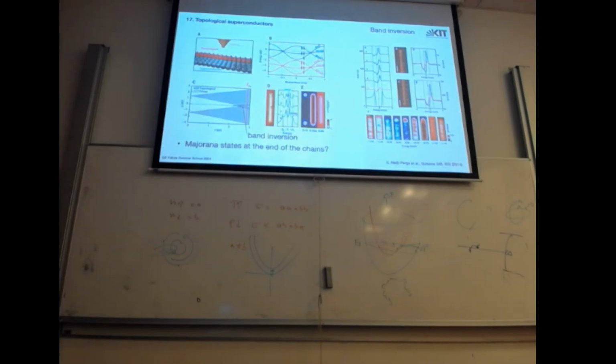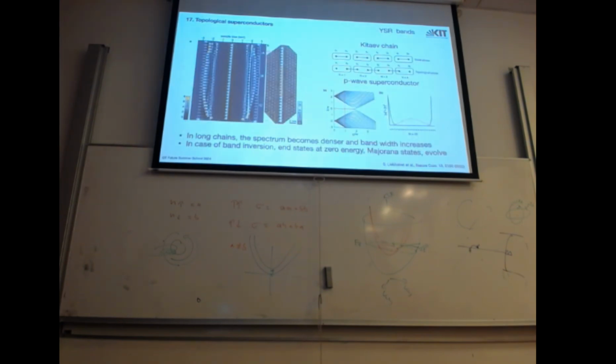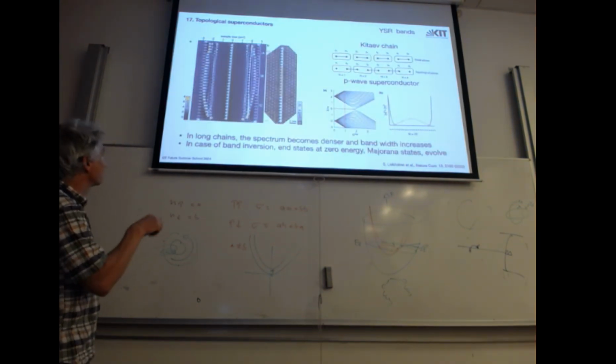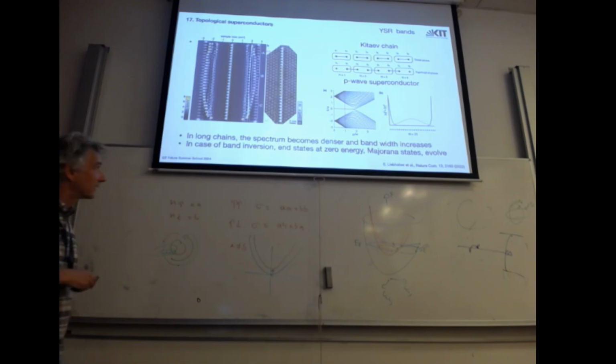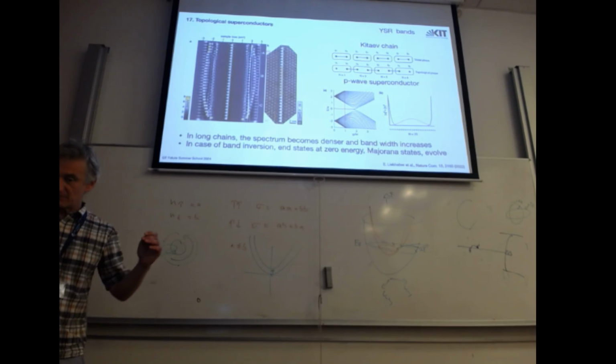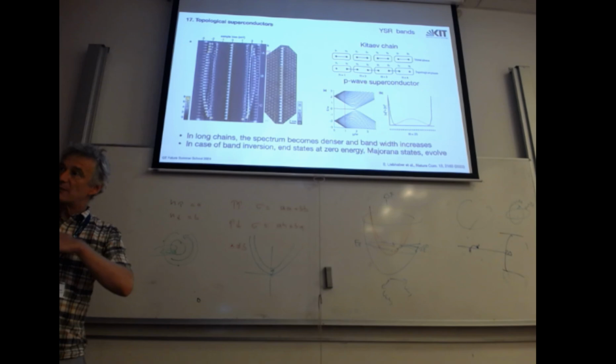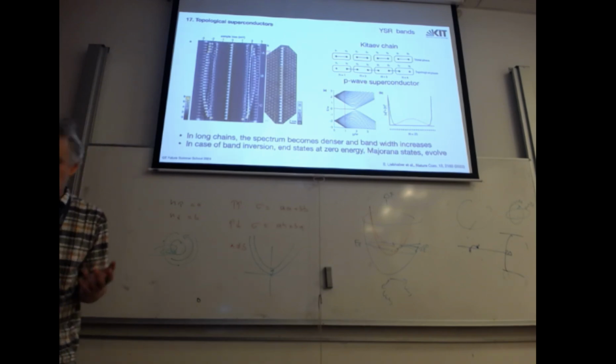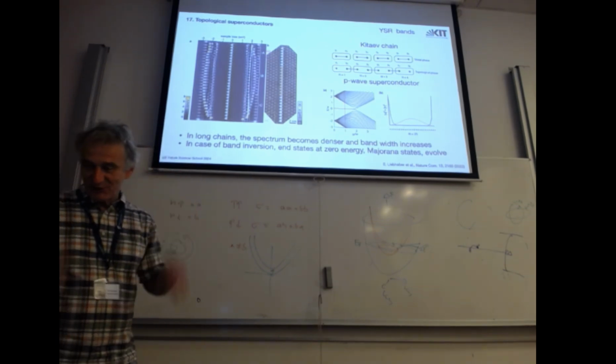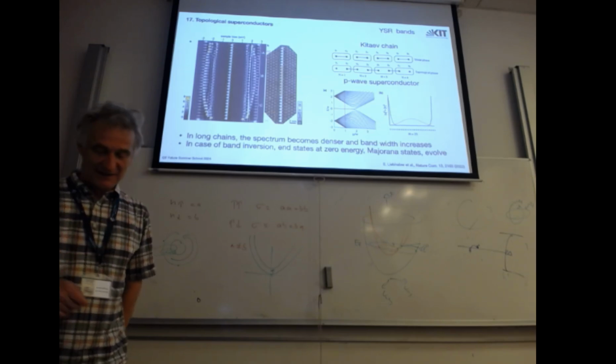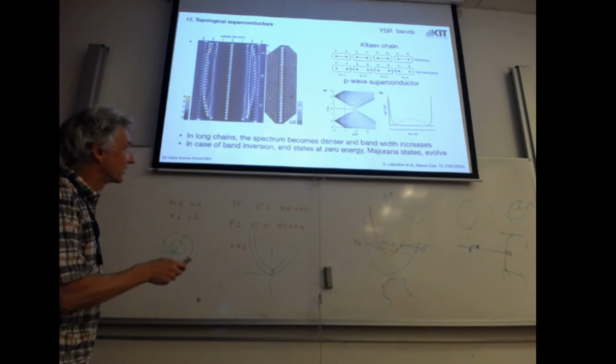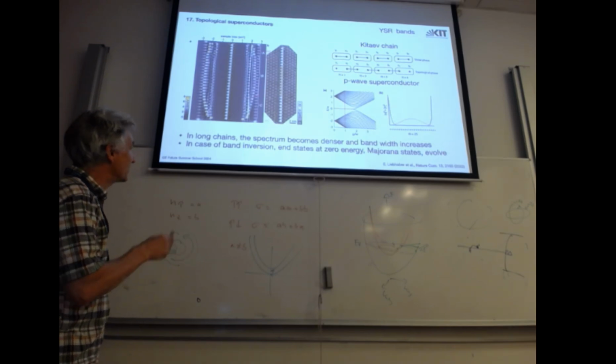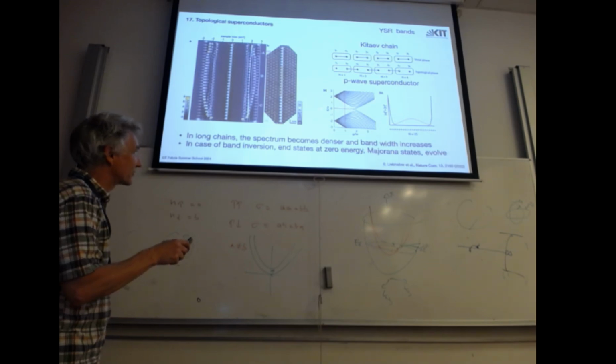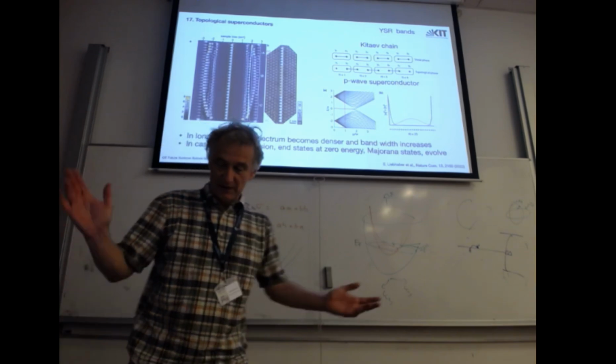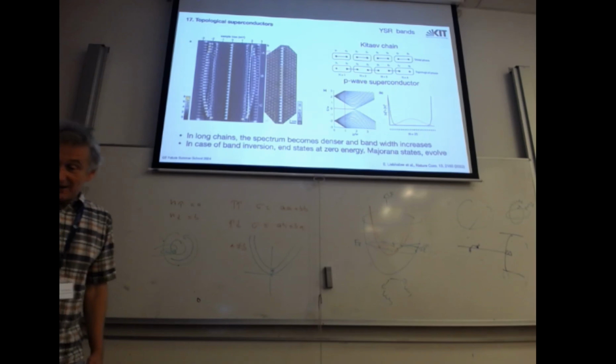And so I would say the experimental observation is that we need a band inversion. So this is a very short chain. And we need a band inversion of these hybridized Shiba states, and maybe this band inversion is never reached. That's maybe at the moment the consensus, but as you don't have the entire chain yet. If you change the bandwidth of these Shiba bands, you get this inversion, and only for certain parameters you get the Majorana states. And it seems not to be realized so far in nature. That's the end, and I'm over time.